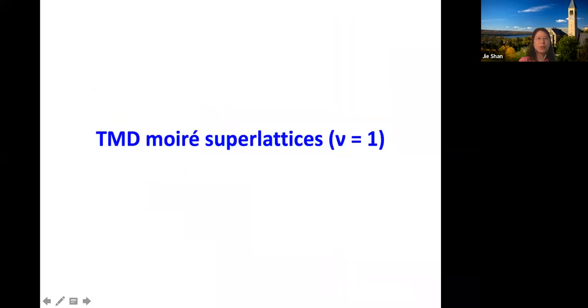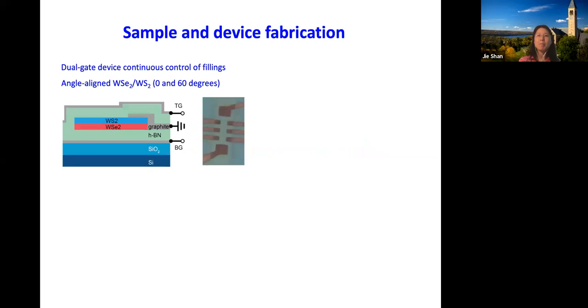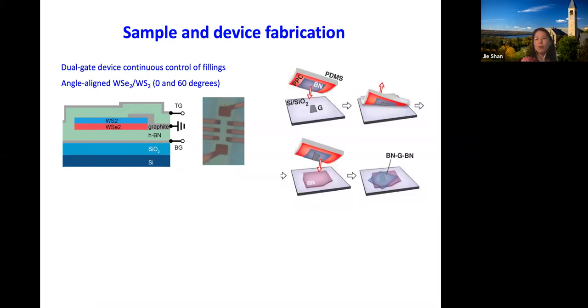So now let me get to the experimental aspect. I first focus on the nu equals 1 case. I think I need to speed up a little bit. Here's our device structure. We have the twisted or untwisted 0 degree heterobilayer, and we have hexagonal boron nitride and few layer graphene as top and bottom gate. And this is how the device looks. The fabrication is very similar. We followed the steps people use to fabricate graphene. The only complication here is that we need to align those two different materials.